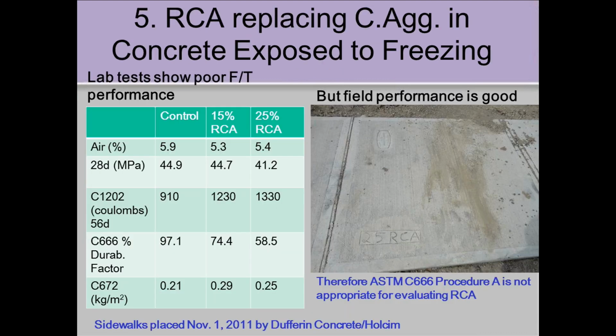We've done some trials on sidewalks, just about this time last year, up on one of the highway interchanges that is being updated, and we're using increased percentages of recycled concrete aggregate replacing the coarse aggregate. We only used 15% and 25% replacement to see if it could be used in concrete exposed to freezing and salt exposure. It's only been out there a year, hasn't been exposed to salt because the intersection isn't open yet, but has been exposed to freezing.